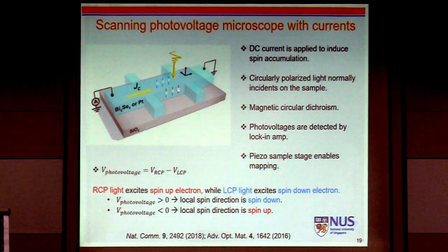So in a defined channel, once you apply DC current, you can accumulate spin up and down, separated. Then we shine circularly polarized light, and depending on the polarization, the amount of absorption will change depending on the local spin population. This principle is called magnetic circular dichroism, MCD, which X-ray people use every day to image magnetism. Then we measure the photovoltage in the longitudinal direction, and subtract the right-hand and left-hand signals.